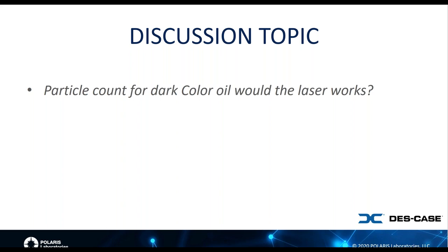Yeah, definitely. I don't want to date myself, but for dark color fluids like engine oils, particle counting was a no-no way back when. Will the laser particle counter work, as the question asks? Yes, it will work, but it will show you a large amount of particles because of the agglomeration of oxidation and degradation particles, even metallic particles, will be so large that you will actually get a real, real high particle count.